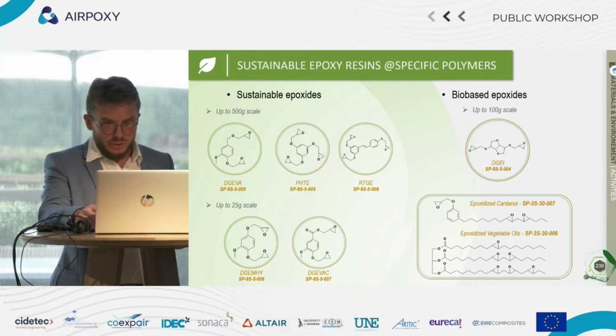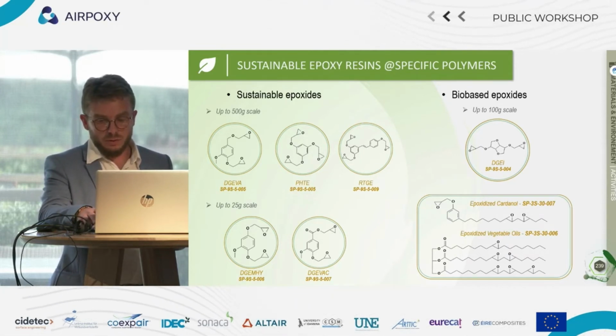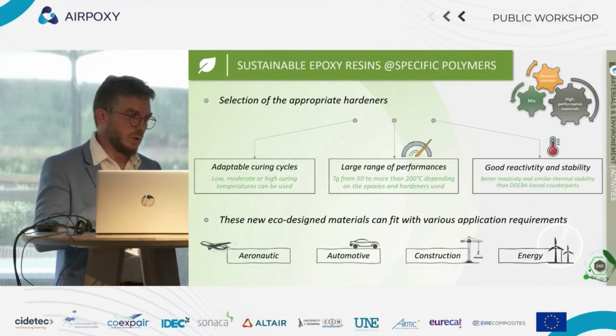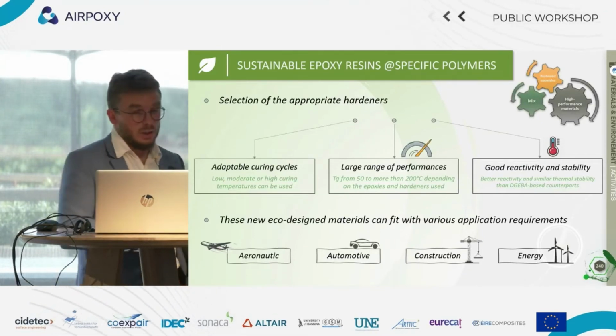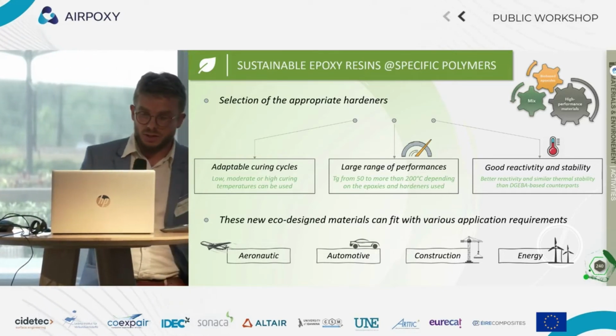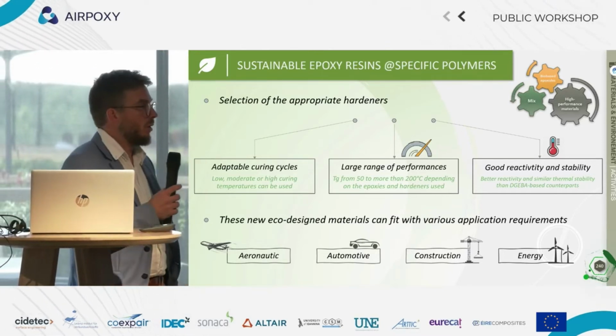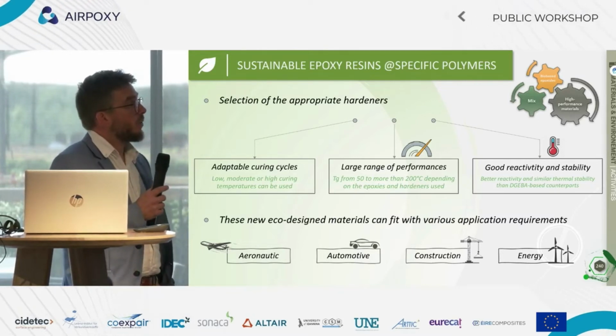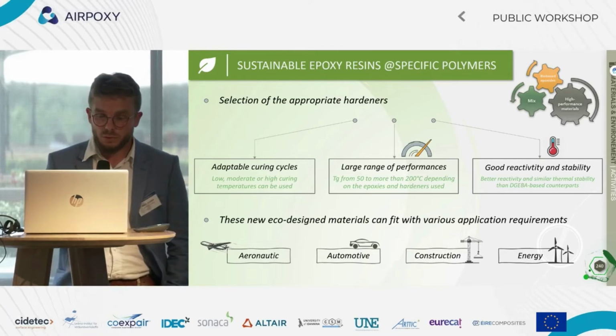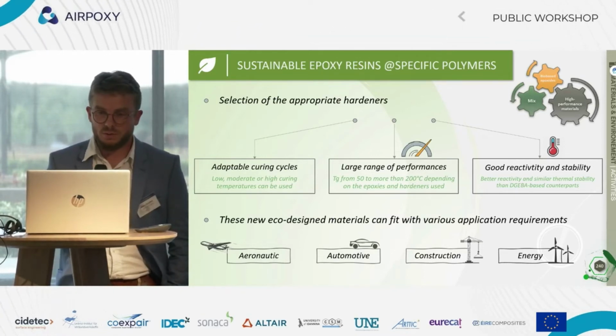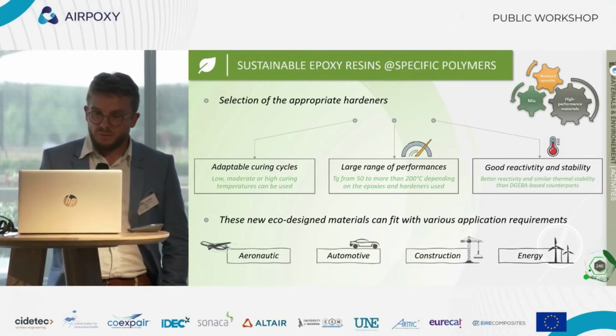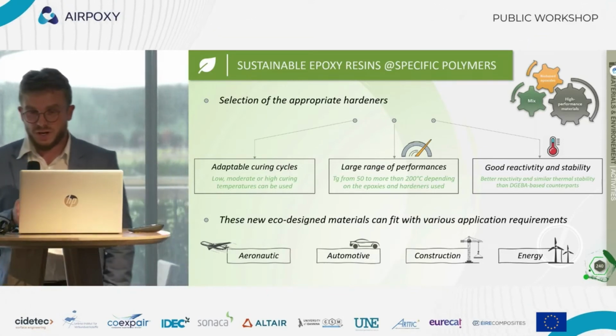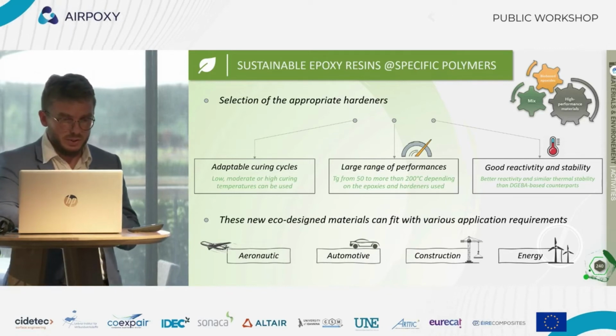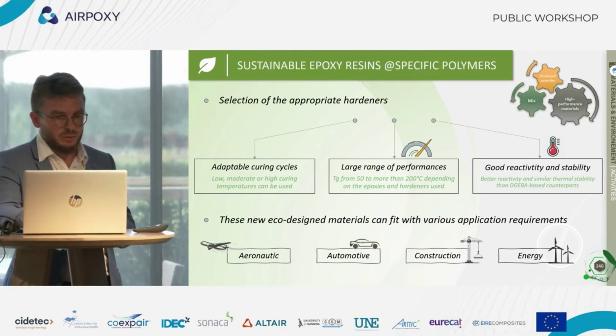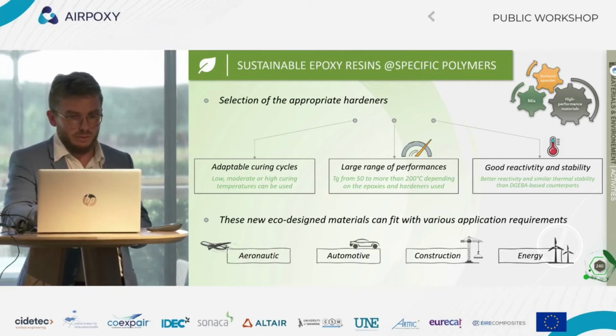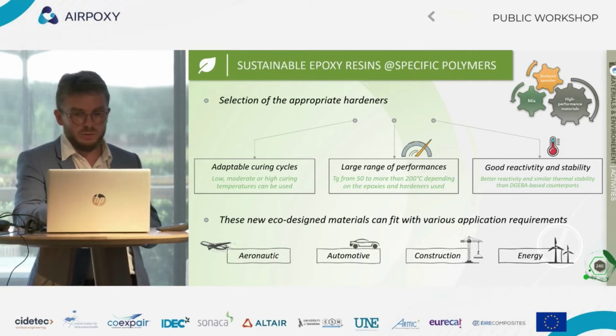So we have these precursors, these epoxy building blocks, and then we work on their formulation to address some business cases. So each time the idea is to tune the resin composition and to assemble all the precursors in order to reach first the process specification. So for instance, adapt the curing cycles, adapt the performances, have the proper reactivity and stability depending on the processes. And then we address, depending on the project, this resin to different kinds of application, mainly in aeronautic, automotive, construction, and energy.